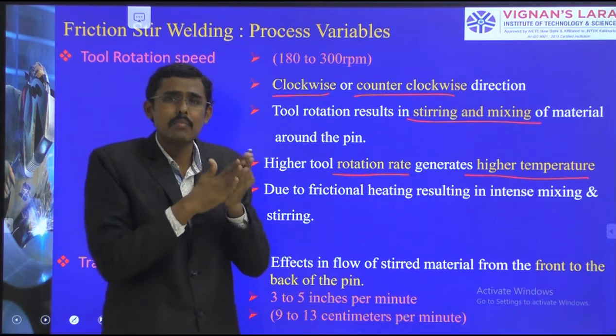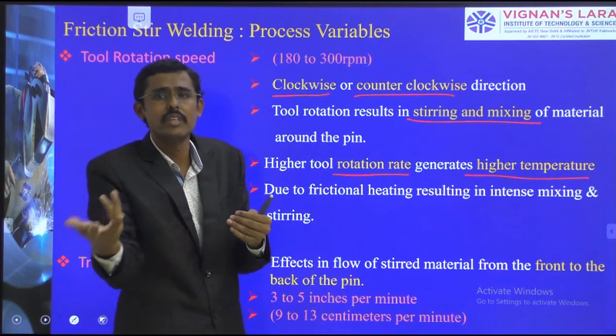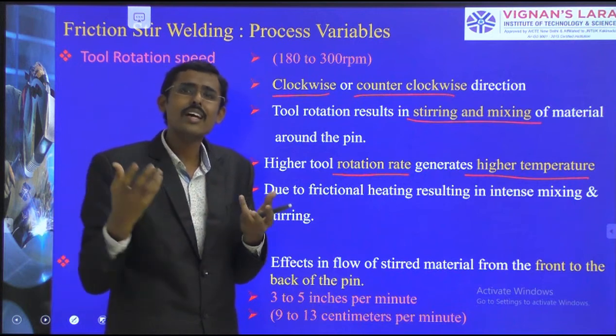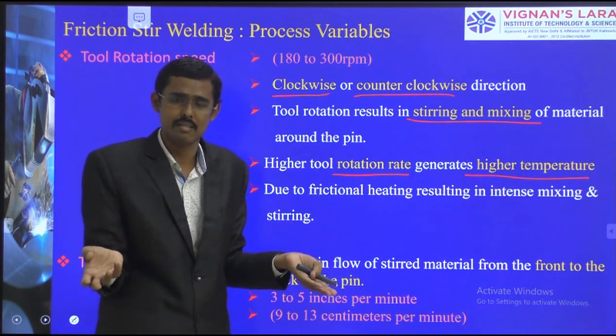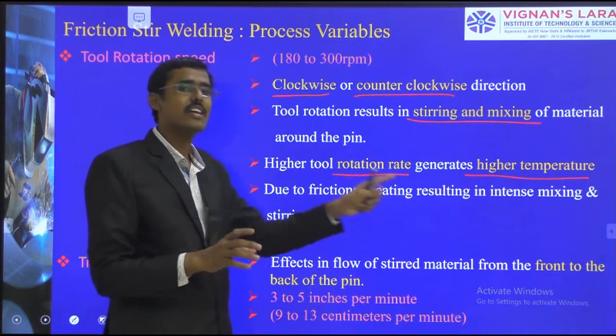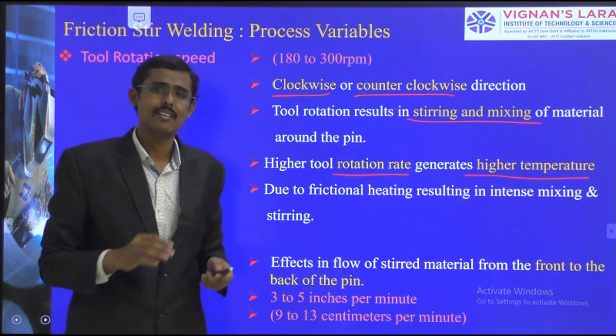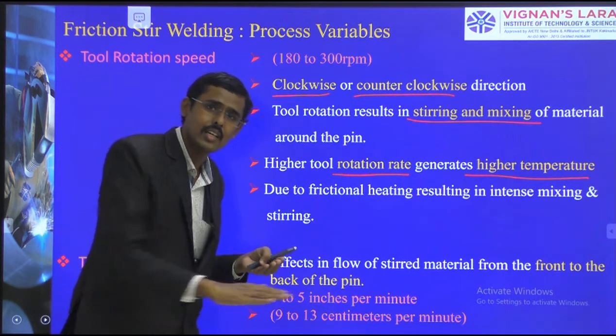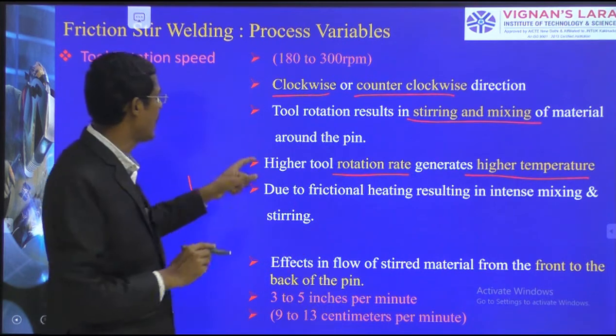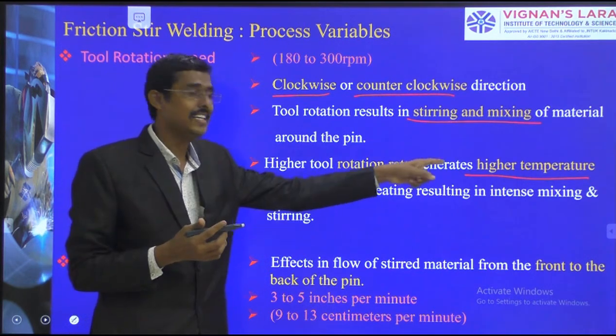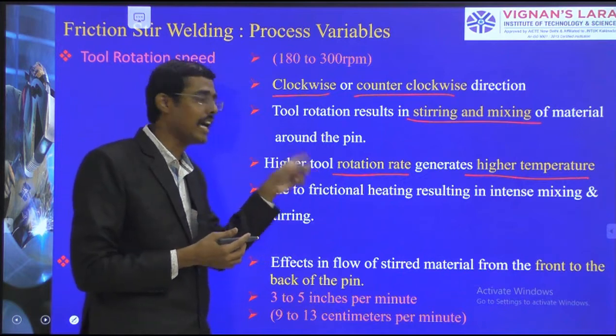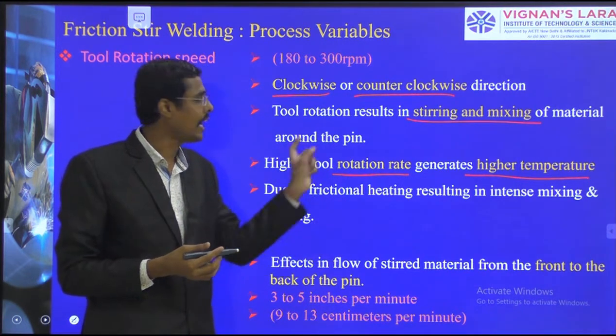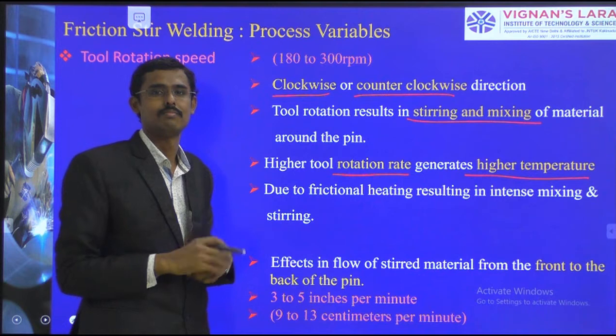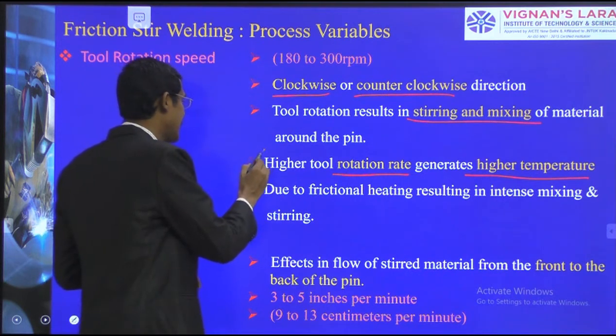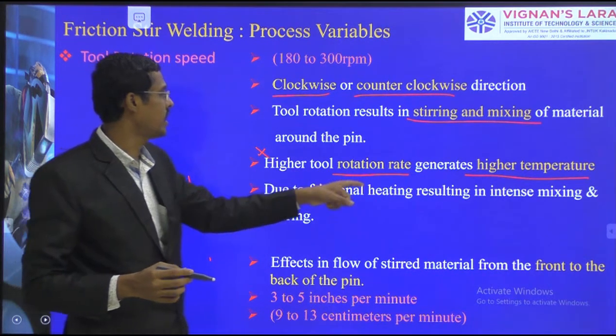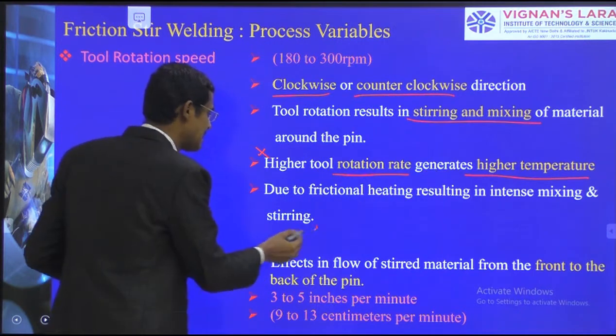Then only it won't melt and it won't wear. If it is worn by such actions, what happens? The pin will wear out. Then where is the pin to rotate? The pin will not be there. Therefore, a high wear resistance material is to be selected as compared to the material being welded. So that is why high tool rotation causes high temperature. If we take an aluminum tool for aluminum material at high temperature, it will melt. It should not, this is to be taken care of. Frictional heating results in intense mixing and stirring.